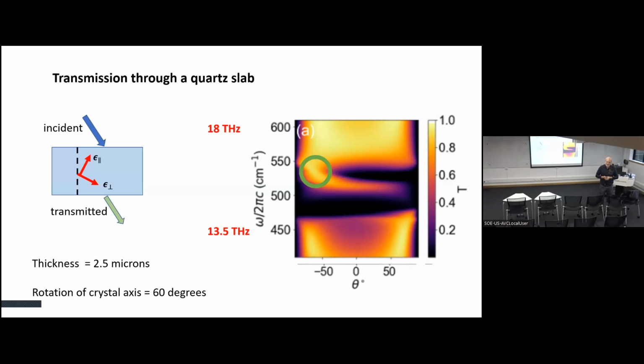It's a variety, in a sense, of the Faraday effect, where imagine you have a cylinder and you bring in an electromagnetic wave, which maybe is circularly polarized. The one sense of polarization will go through with one frequency and one wave vector. The other sense of circular polarization will go through and it will be different. And it is all based, again, on these off-diagonal components.